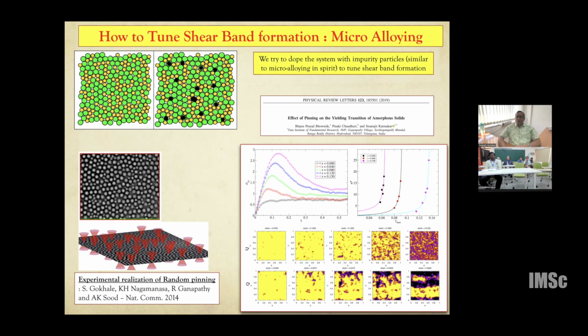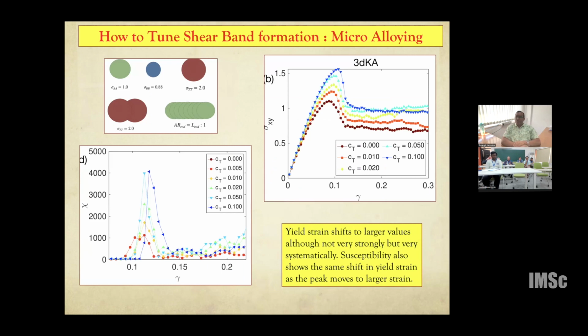So then the next question that we had in mind was how to do microalloying which would be applicable even in, let's say, experiment, because this kind of random pinning would be impossible to achieve. This is doable in colloidal experiments, but not in molecular experiments. So we proposed that if we introduce particles which are bigger in size, then these big particles will have relaxation times which are much larger than your host. So they will have a much smaller diffusion coefficient than the medium particles, and over a time scale of the medium relaxation time, these particles can behave like soft pin particles.